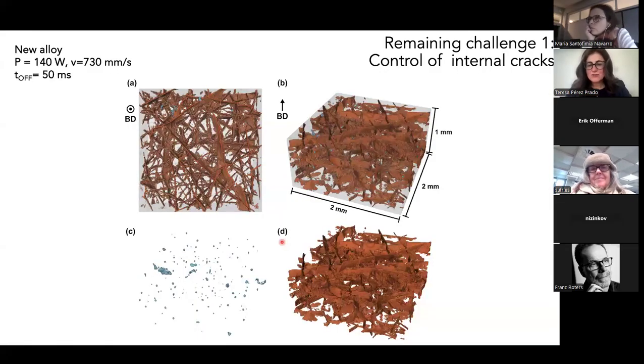One is that so far I highlighted the presence of some cracks, but only using optical microscopy in 2D. So of course we cannot get a very accurate view of the crack structure. If we do some tomography, this is the new alloy manufactured with time delays under a condition where we get a fully amorphous structure. But when we use tomography to investigate the crack structure, this is what you see. It's a very complex distribution of cracks. This volume comprises both the pores in blue here, and here are just the cracks. So we just segmented them. But this is something that we still need to control.